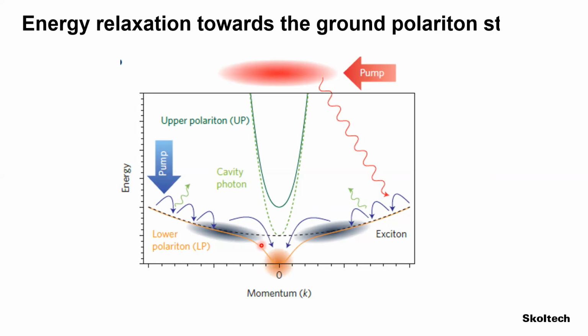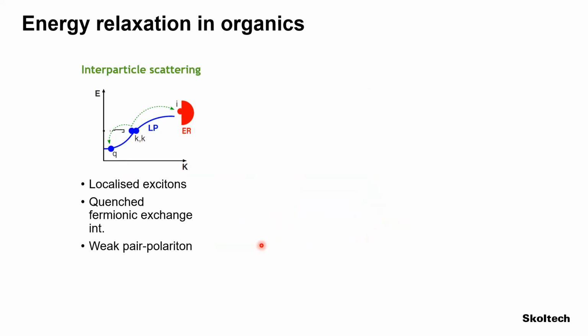Okay, so how do polaritons lose energy in organic semiconductor microcavities, in organic polaritons? Well, in general, one of the main processes when we are dealing with excitons is that of the fermionic exchange interaction. However, when you are dealing with organic semiconductors, that's when you go for room temperature, large exciton binding energy, you have localized excitons. Every molecule is populated by one exciton, and therefore exciton-exciton interaction, the fermionic exchange interaction, is quenched. So you have very weak polariton-polariton interactions. That is actually a limiting factor which is present in organic semiconductors, but not in bulk inorganic crystalline semiconductors.